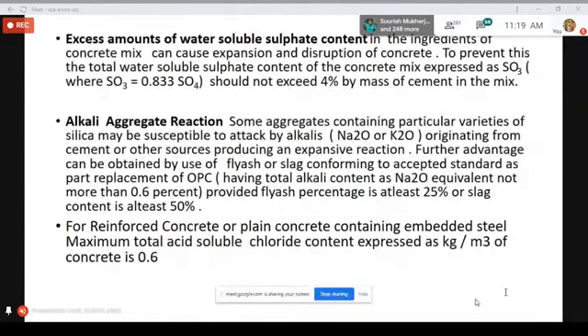Chloride content is normally found in places near the coastal areas. And one needs to be very careful as far as the attack of chloride is concerned, because chloride can attack the steel in RCC structures. That's why you will find that the soluble chloride content should be 0.6 kg per cubic meter of concrete, and water soluble sulfate content should not exceed 4% by mass of cement as far as the concrete is concerned.